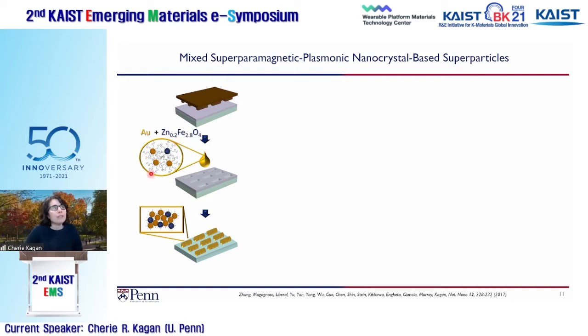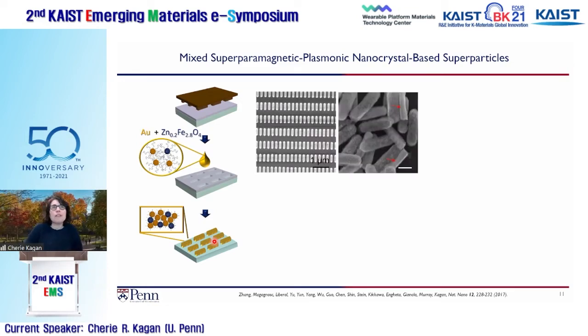What we did is, if you mix them together, we could make these rod-shaped structures, we sometimes refer to them as superstructures, where they're combinations of both metals and magnets. This is an example where we did the imprint lithography, harvested them from the surface, and suspended them in solvent. This is when we drop them back down. You can see the rods, and you can see some graininess characteristic of the nanocrystals in the material. And we could do that same kind of ligand exchange.